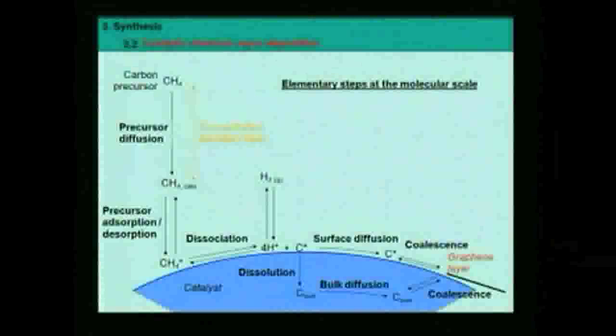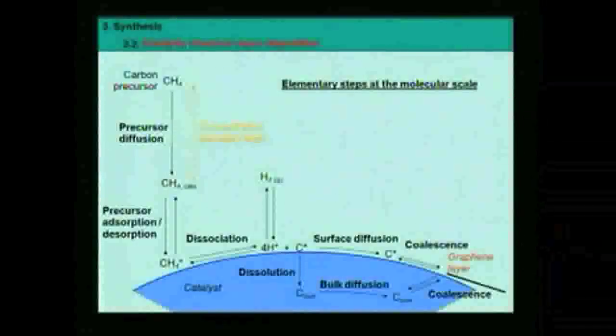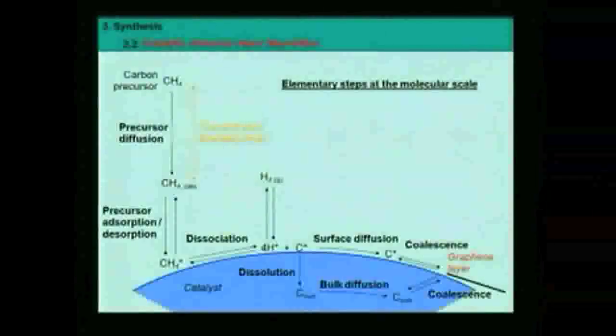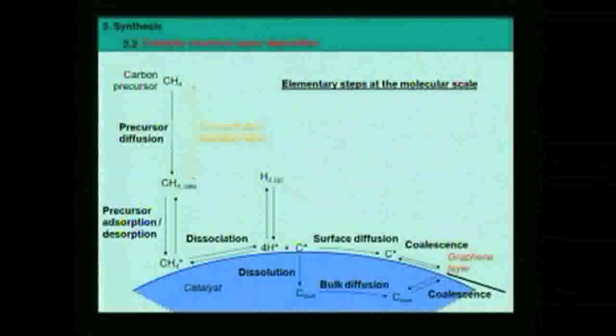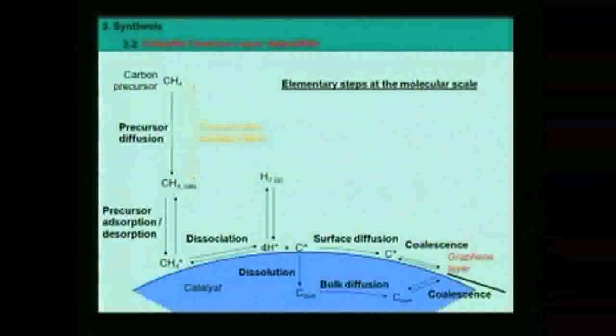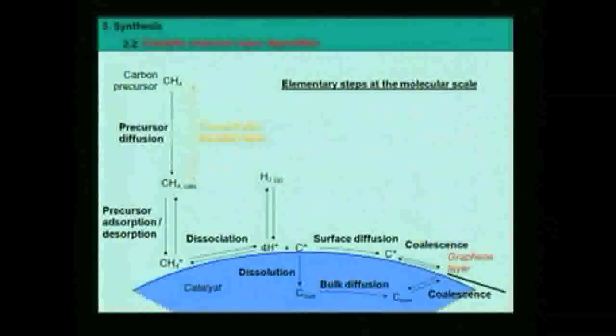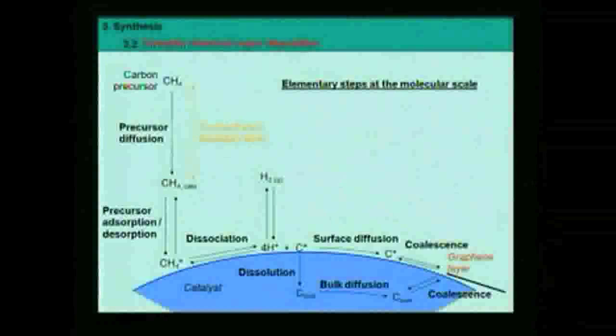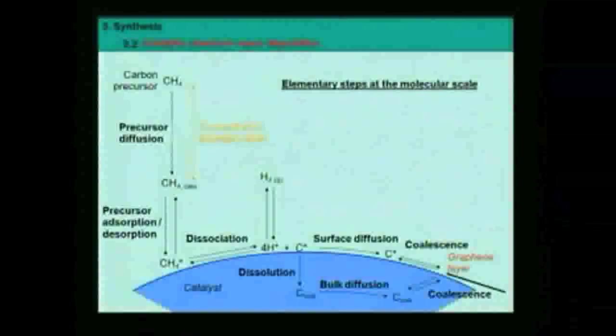What will happen? You've got this precursor. As an example, I took methane. This methane, to react with the catalyst, has to diffuse in the gas phase. So this is also called mass transport, gas phase mass transport. It diffuses to the surface. Now it is close to the surface. If it has a good sticking coefficient, it may adsorb on the surface, but also once adsorbed, it could desorb. We have an adsorption-desorption equilibrium between methane adsorbed on the surface and methane in the gas phase.